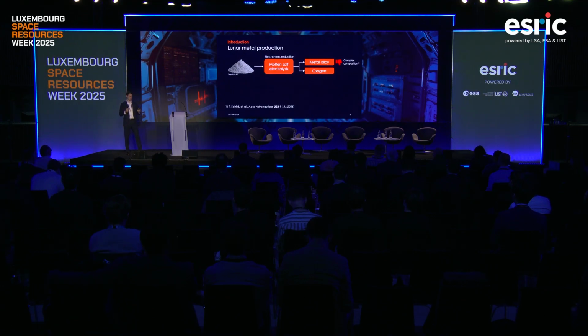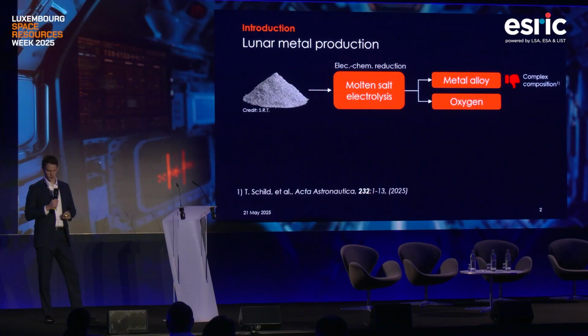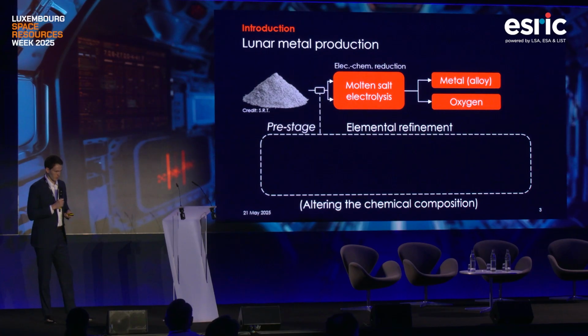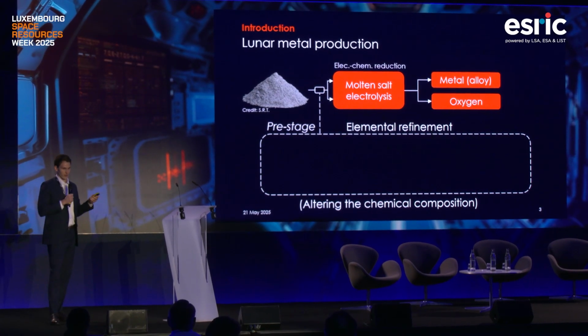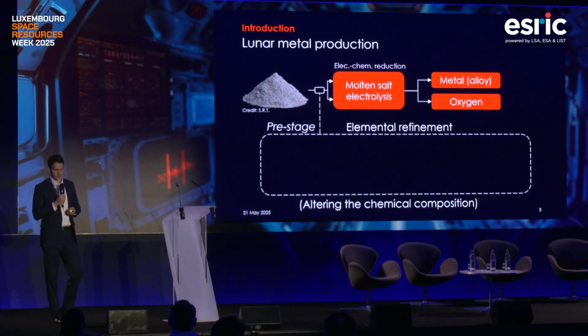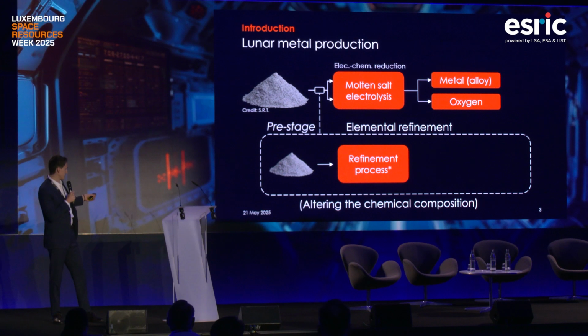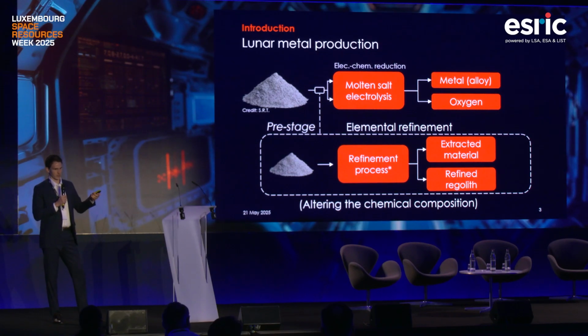However, the alloys that we produce have a very complex composition and are very hard to deal with. And in order to prevent that, or to create better, higher purity metal alloys, we propose to put a pre-stage in front of various methods, such as electrolysis, to refine the regolith. So the idea is to put the raw regolith through this refinement process, really extract some materials on the elemental level, so alter the chemical composition, and then end up with, for example, 2 separate feedstocks that we can individually feed into an electrolysis reactor to produce higher purity metal alloys.